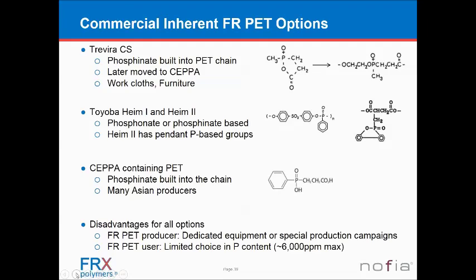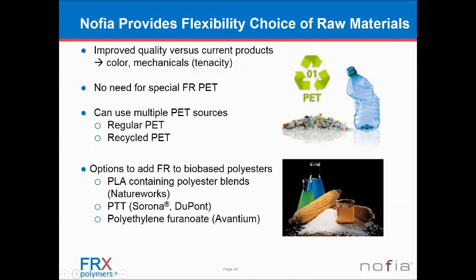But overall, you can look from two directions. There are some disadvantages to these materials. The producers of these types of materials typically make them in campaigns. So they typically make polyesters and then switch over to building these monomers into the polyester. But there is a limitation to the amount of phosphorus that can be built in, typically about 6,000 ppm. So you also have limitations to the stringency of the flame retardance test that you need to meet, and you're restricted to 6,000 ppm.